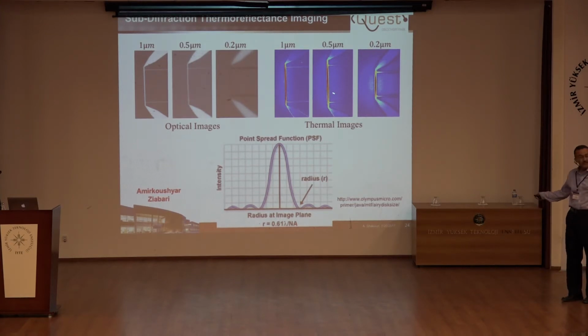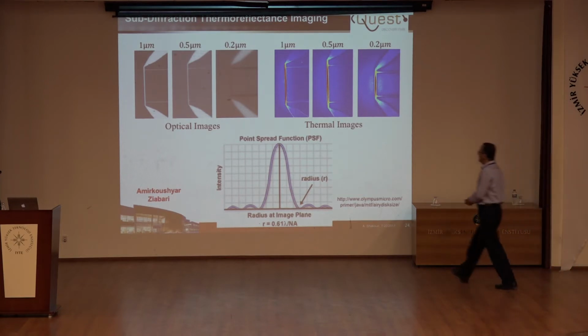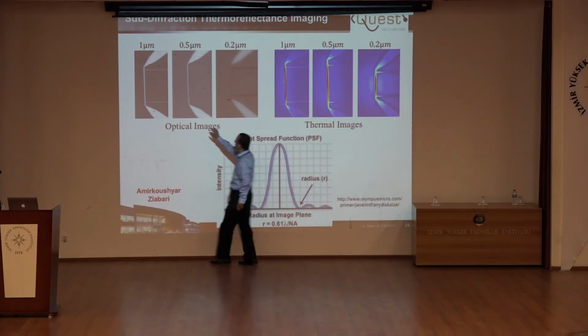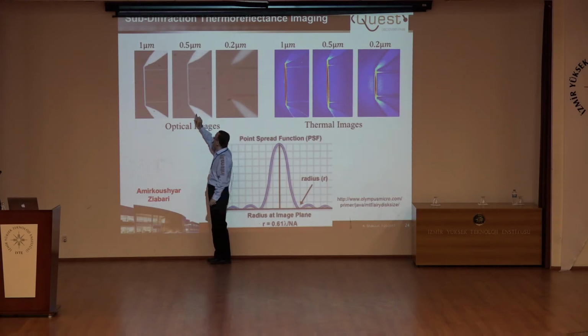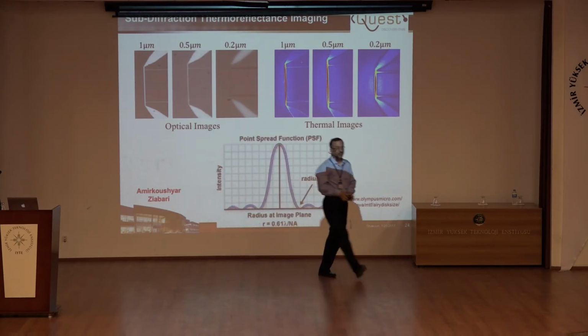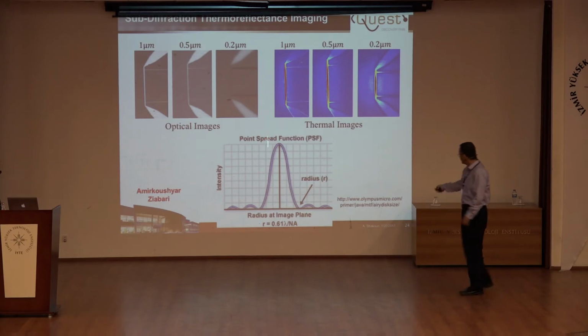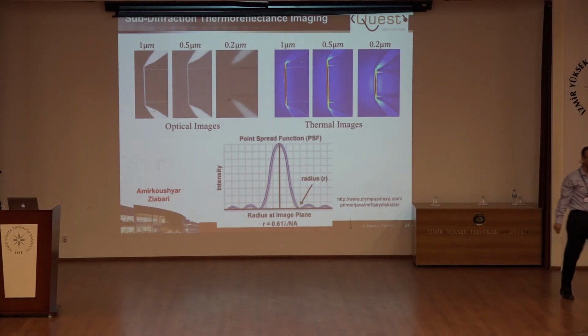Why is it that we can see the signal from a tiny device, even if it's below the diffraction limit? It was pure luck. What I mean by luck is not that it happened once and doesn't happen again. What I mean is that the metals that are made here have a thermoreflectance coefficient that has a different sign from the semiconductor. So as the device heats up, here is brighter than here, but as the device heats up, the reflection coefficient of this one goes up and the other one goes down. And whenever there is a phase change, you can go below diffraction because this is amplitude squared. Before squaring it, a lot of things could happen.